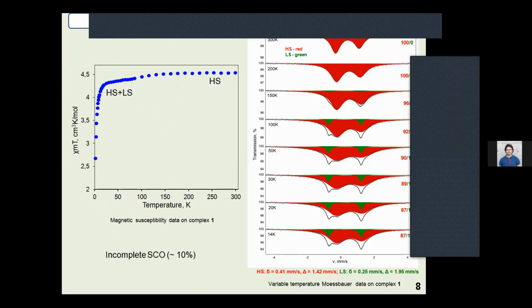This assumption is in good agreement with magnetic and Mössbauer data, demonstrating the ratio 92% high spin to 8% low spin at 100 Kelvin. χT is almost constant over all the temperatures, and the small lowering of χT can be explained by the presence of the low spin fraction at this temperature.